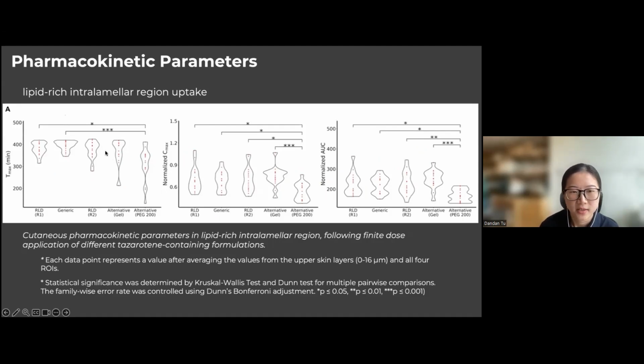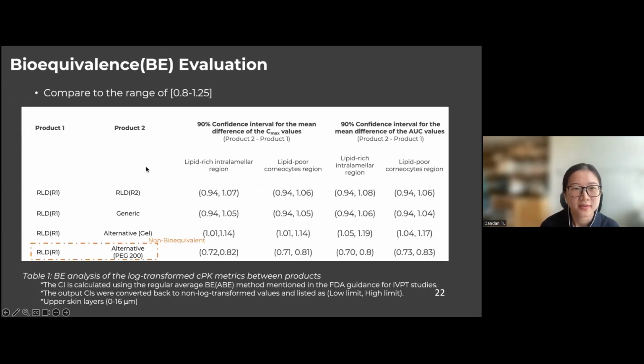And for the Tmax value, we observed that the alternative formulation composed of PEG 200 shows a statistically significantly different Tmax value compared to the generic and the reference listed drug. And for the Cmax and the AUC values, the PEG 200 group shows statistically significantly different values compared to the rest of the groups. And this is the main part of the bioequivalence study.